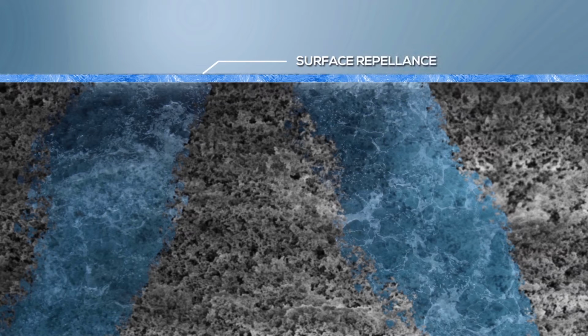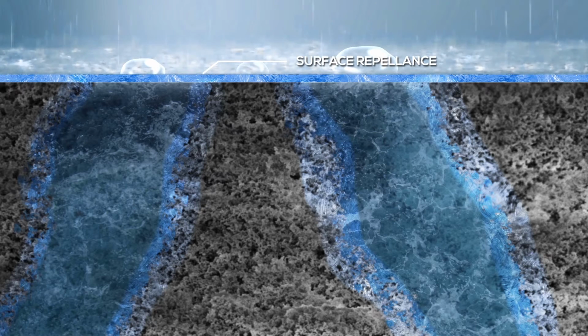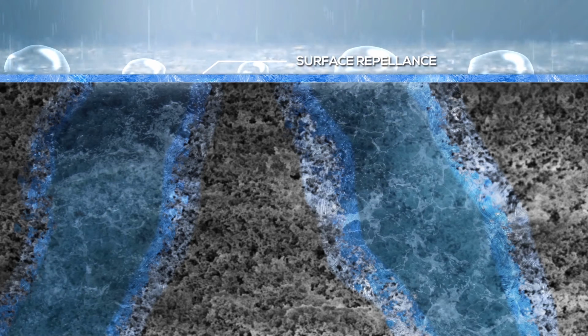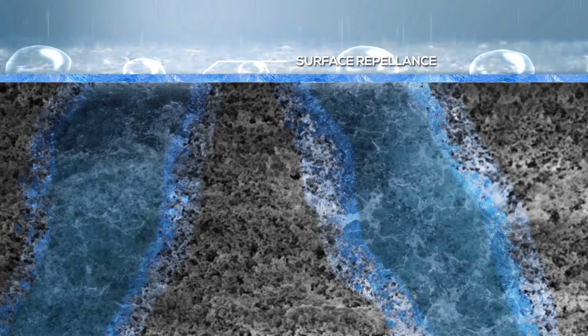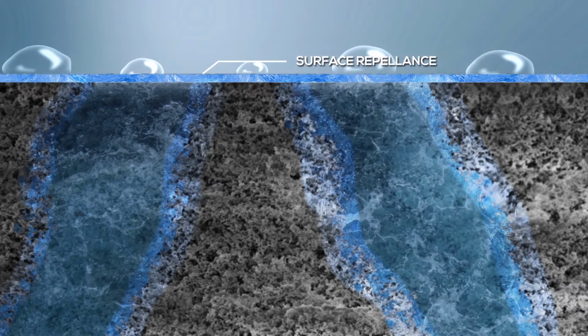The initial reaction that takes place once the Supershield Multiseal starts drying on the concrete surface is an excellent repelling feature. This takes place when the product reacts with the carbon dioxide in the atmosphere and forms an invisible film on the surface and on the inner walls of the pores. This prevents water from penetrating into concrete through capillaries by increasing the surface tension of water and other liquids such as jet fuel and oils.